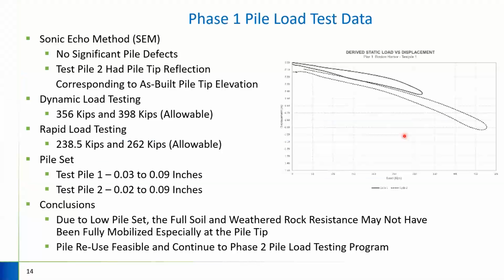So getting into the results of the program, for the phase 1 load test data, we used sonic echo method testing initially just to determine if there were any significant defects in the pile. And should there be a significant defect in an individual pile location, we had alternate locations to go to that we would address at that time, but we did not need that for the phase 1 program. One item of particular note for the phase 1 program was that we ended up getting a pile tip reflection from the sonic echo method testing for test pile 2 that corresponded to the approximate as-built pile tip elevation within plus or minus 2 to 3 feet. We did not see that at test pile 1. However, it did not note any significant defects, so we moved forward with that test.